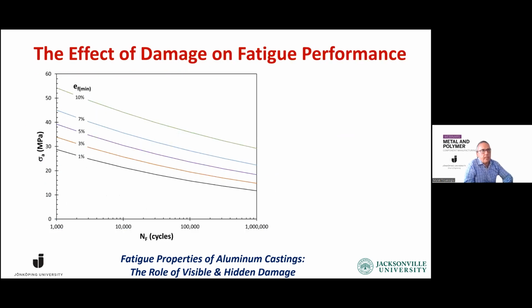So here we have some SN curves. We start with 1%. This is our SN curve up to 1 million cycles. And what if we increase our expectation to 3%? What if 5%? What if 10%? What does that mean? Here we are looking at a quality index of 0.034, which means 96% loss to damage. We think that that's okay in our castings right now. What if we say I will tolerate only 66%, or anything in between?